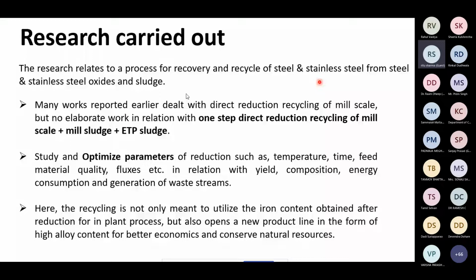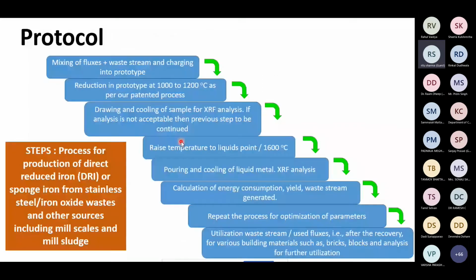Many works reported earlier dealt with the direct reduction recycling of the mill scale, but no elaborate work relates to the one-step direct reduction recycling of the mill scale plus mill sludge plus ETP sludge. All three together for direct recycling is not carried out. Study and optimization of the parameters was also carried out, and let me show you the protocol. We have followed these steps so that the mill scale and mill sludge can be directly analyzed.